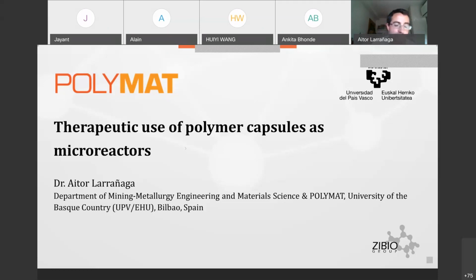Yeah, that's a really nice question, and this is precisely what we are trying to do now. Because of course, if you incorporate a drug or you change the structure of the polyelectrolyte that you are using for the fabrication of the polymer capsule, then that could have an impact on the stability, and that is something that we are trying to study now. In the first example, it is true that we combine a large molecule such as catalase that is 250 kilodaltons with a small molecule, tannic acid. So this is more or less the procedure that we want to follow to go for combinatorial approaches that can target more than one mechanism, because targeting one single mechanism is quite a simplistic view of a complex pathology.